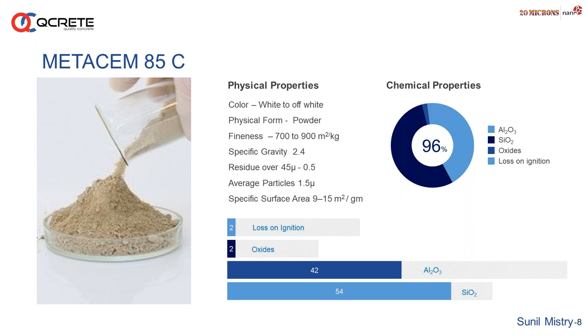Specific gravity is almost 2.4 to 2.5, and you can see on the screen the particle is very fine, 1.5 to 2 microns. We control this particle size distribution right from raw material in process, and after the calciners we also do secondary grinding to get a consistent particle size distribution. The specific surface area is between 9 to 15 square meters per gram.